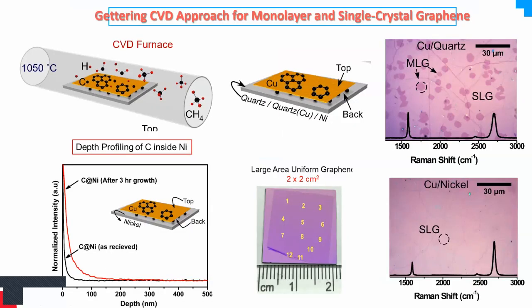So to make it a more sophisticated growth experiment, now I put copper onto different types of substrate. One is just quartz, like in a quartz tube, and one I put on nickel. So when I put this copper foil on nickel and then grow inside the tube, I can see that when I put the copper on quartz, it gives me again single layer graphene along with a lot of multi-layer patches. But once I put copper on the nickel, I can see only clean single layer graphene grows with this kind of configuration at the bottom.